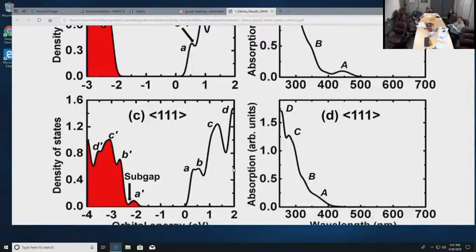Because here, probably this one is the gap transition for absorption, and it is bright. Right? So the emission probably will peak at the same place. And here, the gap is about here, but it is dark, and emission will be in this region where there is no absorption. Therefore, the intensity will be lower. But also, there is a chance that there will be a contribution to emission not from the lowest transition, but slightly above. Maybe here. There is also.